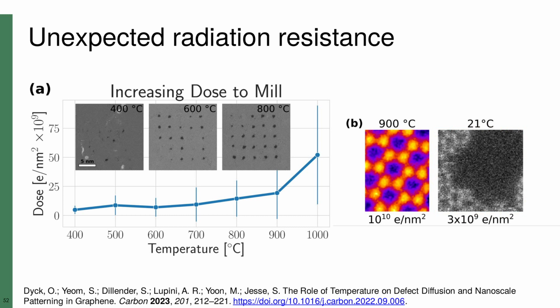Perhaps some residual hydrocarbons can still make it into our corrals and heal the graphene, making it more difficult to mill. As we increase the temperature, we are increasing the supply of these residual hydrocarbons, which increases the likelihood for healing. It sounds plausible, but what does the data show? Let's look at some examples. In each of these examples, we successfully milled a 5x5 array of holes, and then acquired the final overview image shown. What we see is that at lower temperatures, there is significantly less healing than at higher temperatures.